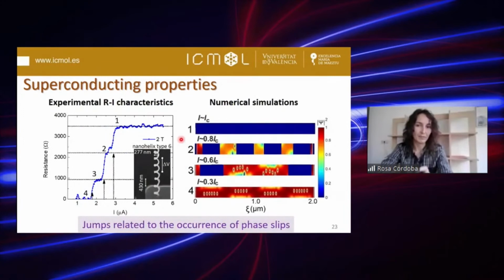And an interesting feature was observed in one of these nanohelices, type number 6, in which we observed the transition from the superconducting state to the normal state happening in different steps, as you can see here. And these steps are related to the occurrence of phase slips. This was our interpretation based on numerical simulations, based on the time-dependent Ginzburg-Landau equation.